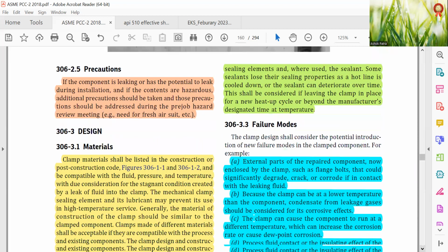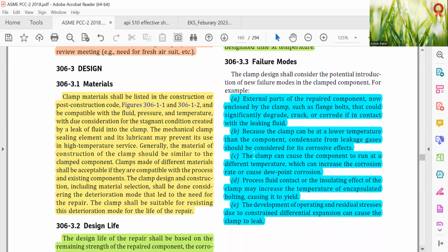Failure modes: external parts of repaired components now enclosed by clamps, such as flanges and bolts, could significantly degrade, crack, or corrode if they contact the leaking fluid. Because the clamp can be at a lower temperature than the component, condensate from leakage gases should be considered for its corrosive effect. The clamp can cause the component to run at a different temperature, which can increase the corrosion rate or cause dew point corrosion.